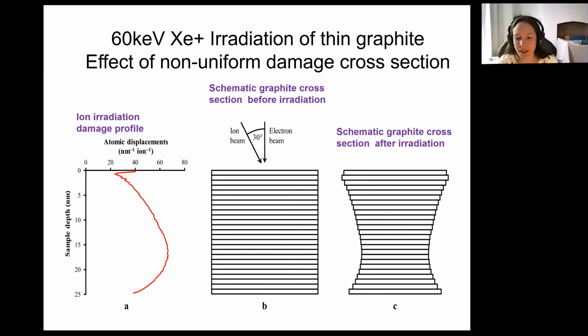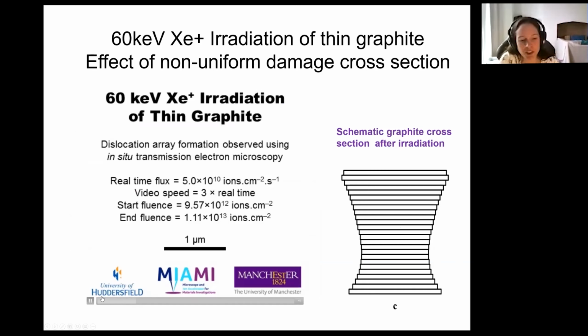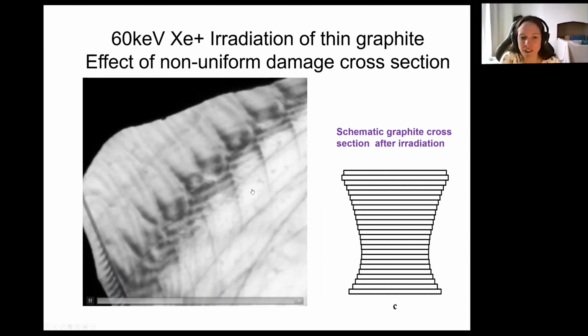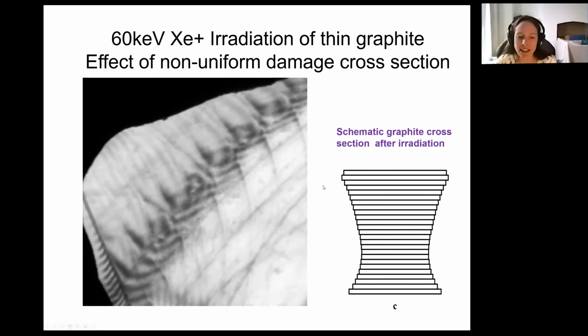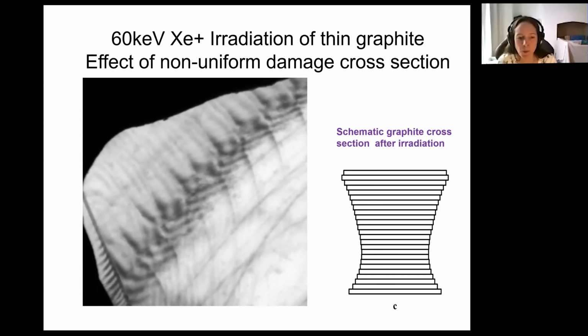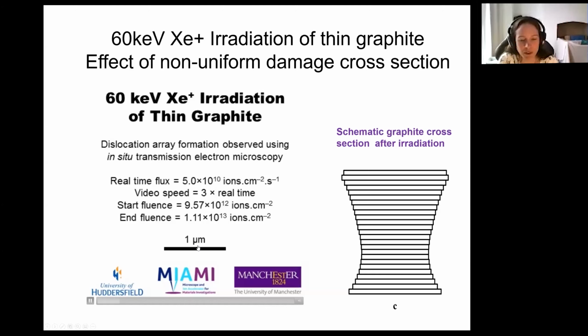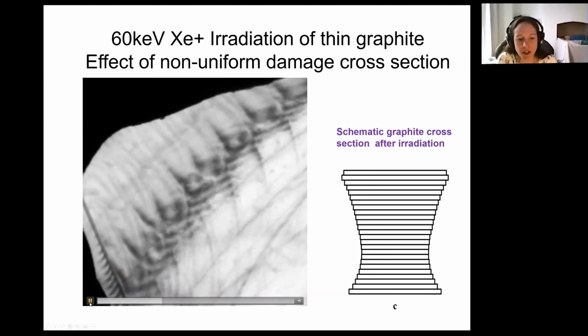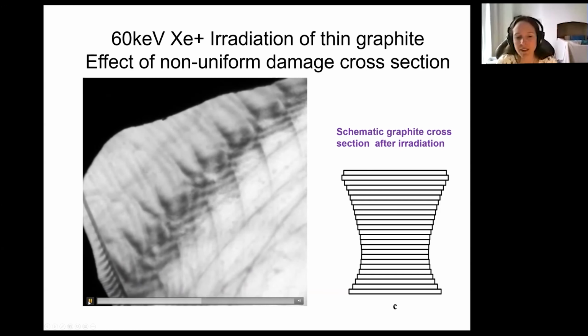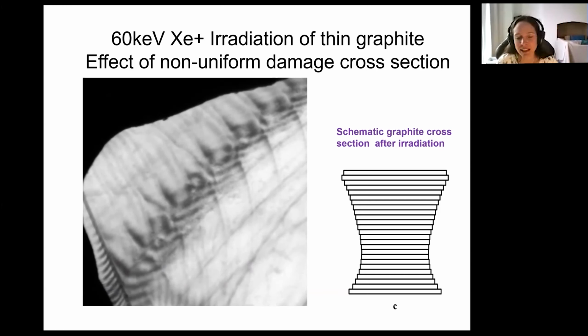But of course here we know that the material is very crystalline, and so it doesn't want to just deform and create a huge amount of strain within the layers. And so we can watch a video of what the material does to try to accommodate this strain. These are dislocation lines, and as the material becomes more irradiated, the dislocation lines move to be able to accommodate that strain. And actually here, what you'll see is when we just run the video a little bit later on. So if we run that video now, we can see the dislocation lines are actually emanating out from this line defect here, and that line defect is very similar to what we saw in the video at the beginning in the SEM system. So as we continue to irradiate the specimen, we can see those dislocation lines increase in density, demonstrating increased strain in the material as the shrinkage occurs more rapidly.